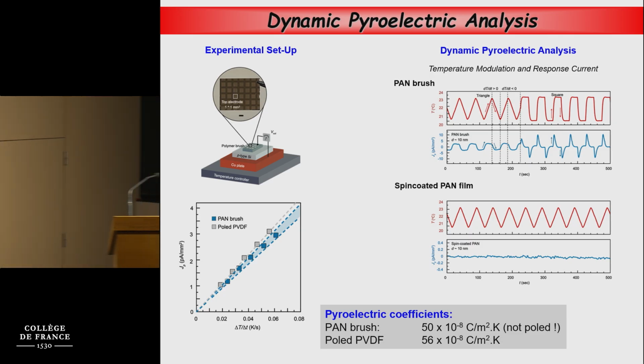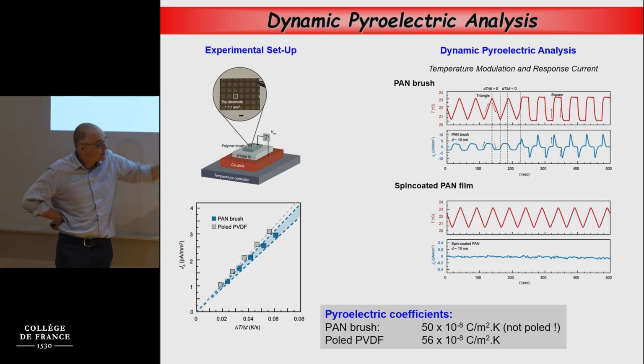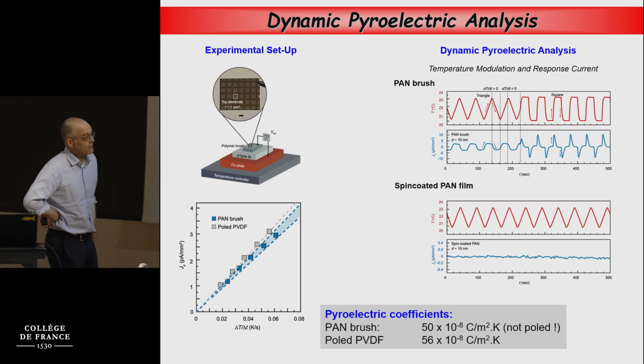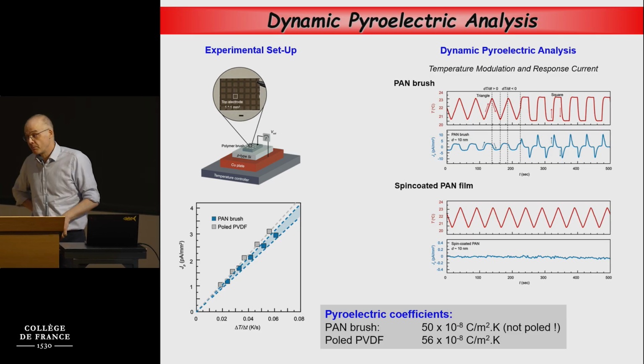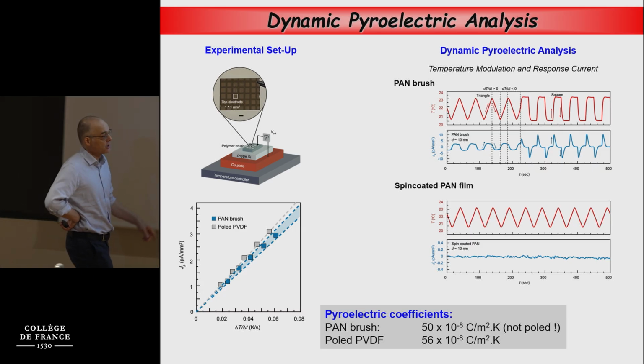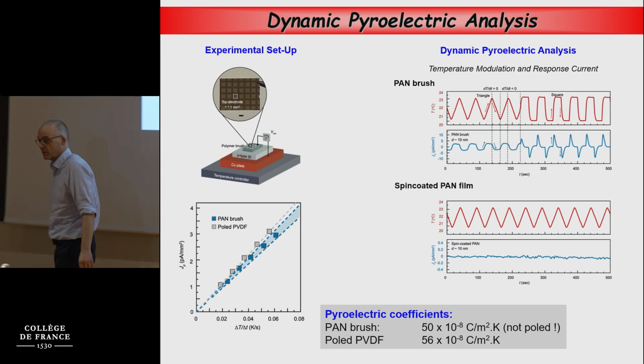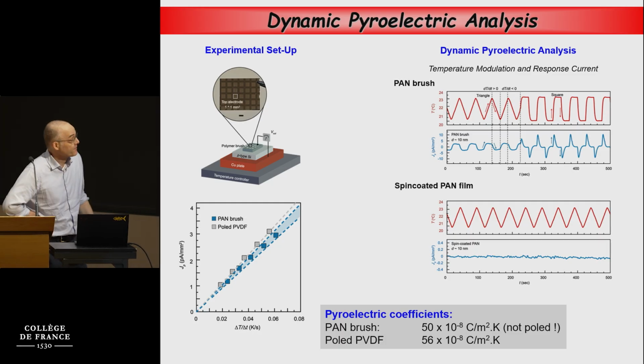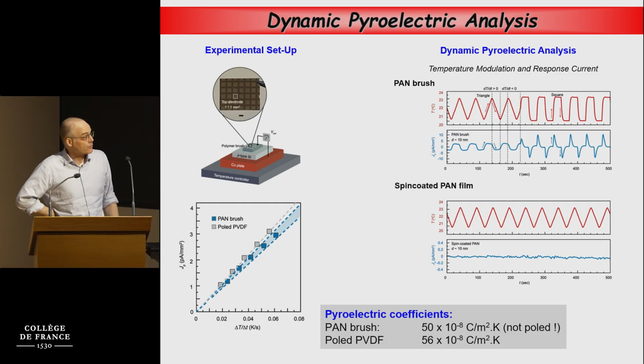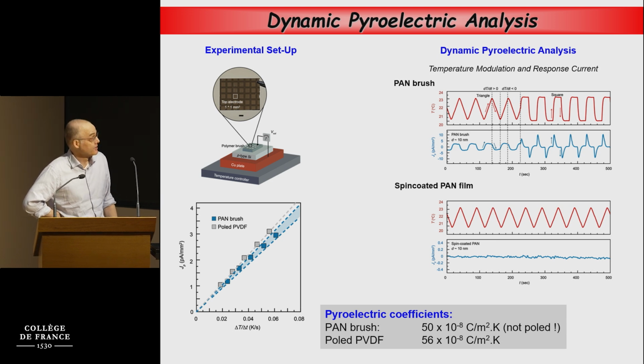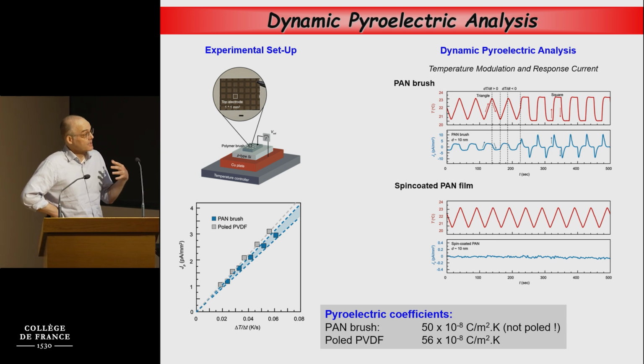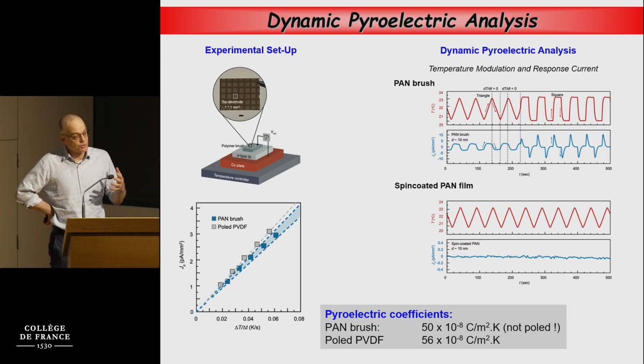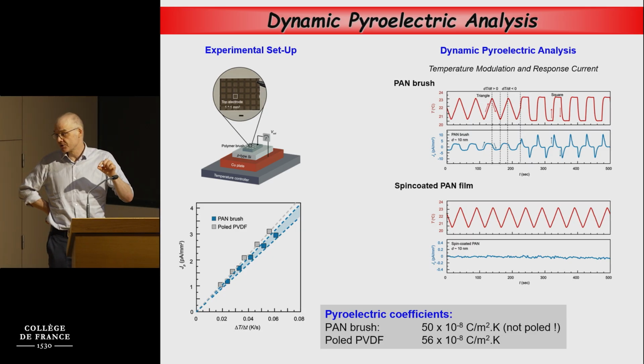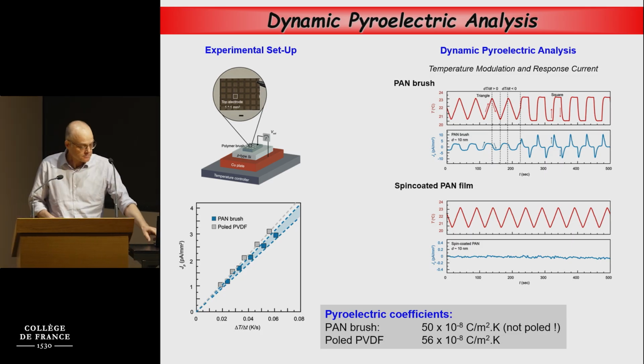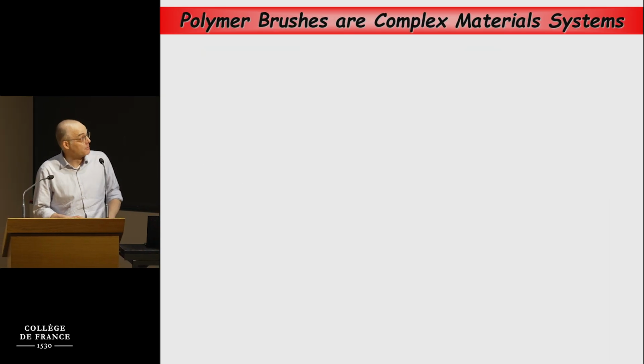And as you can see here, the pyroelectric coefficient of a polyacrylonitrile brush is about 50 times 10 to the power minus 8 coulomb per square meter per Kelvin, which is comparable to a poled PVDF film. But the interesting thing is that this polyacrylonitrile brush is only grown by surface-initiated polymerization, and we didn't have to apply an external field to achieve this. And of course, the spin-coated film doesn't show any of these pyroelectric properties. So I think this is conceptually a bit easier to rationalize. We have molecular dipoles, and this indicates that the surface-initiated polymerization reaction somehow induces spontaneous pyroelectricity.